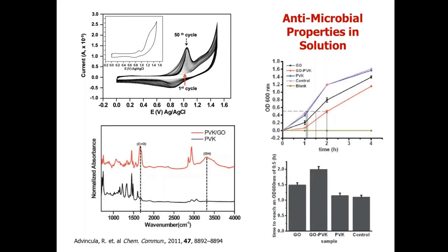In other words, if we have more bacteria, we would have dead bacteria anyway, and we would have a higher optical density, which is the case if we compare the blank versus the graphene oxide versus the graphene oxide PVK. We can basically compare their ability to kill bacteria in one way. The higher the optical density, the higher the time to reach the optical density at 600 nanometers.